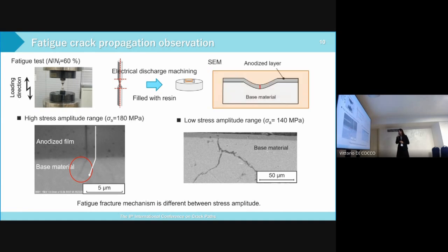The resin-filled specimen was polished and observed by SEM. As a result, in the high stress amplitude range, cracks propagated from the clogging, shown in red circles. On the other hand, in the low stress amplitude range, the crack initiated and propagated from the interface between the anodized film and the base metal. So the fatigue fracture mechanism differs between stress amplitudes.